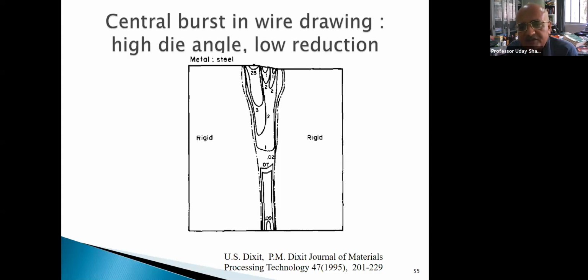Now let us talk about that. Suppose by doing the finite element analysis, other than roll force, roll torque, etc., or in wire drawing, drawing force, the finite element method can give some extra information. Suppose we plot the strain rate contours here. In this particular setting, I observed that this zone was quite narrow; the plastic zone was this much, but at the bottom, for these particular parameters, I later analyzed that if this zone becomes too narrow, it may almost become elastic. So this portion is elastic, but the upper portion is plastically deformed. This situation is prone to give a defect like central burst, in which there will be cracking on the inside. This occurs if you have high die angle and low reduction.